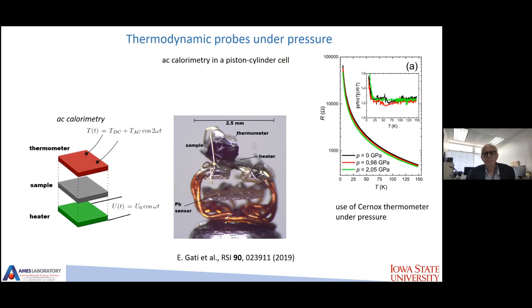Okay, more questions? Russ, one more comment since Sergey has this up. Elena, who I think is still online also, was able to show that you could measure, for example, europium compounds and lead, so superconductivity in lead or a local moment in europium, and we could get semi-quantitative entropy, in the sense of sort of 80% worth. So it was really quite a nice piece of work that brought semi-quantitative specific heat over a fairly wide pressure and temperature range. Well, that's great to hear. I think there's a lot that can be done with other systems, even up to say 3 GPa. I think that's terrific.